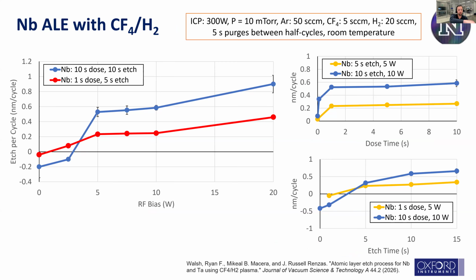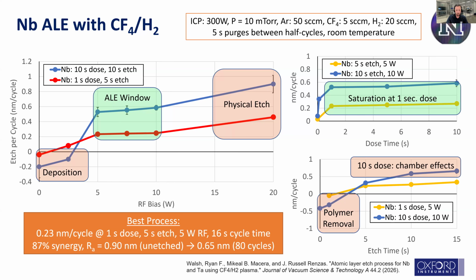We don't even really get etch. However, if we get really high, with a really, really long dose, we have found crazy chamber effects that have caused problems. So there's a really nice regime in the middle where, if we have a 1 second dose and just enough etch time, we get a very stable self-saturating, self-limiting process. We found our best process got us about 0.23 nanometers per cycle at a 1 second dose, 5 second etch, for a 16-second cycle time. This is all niobium, 87% synergy, and we did see a roughness reduction.